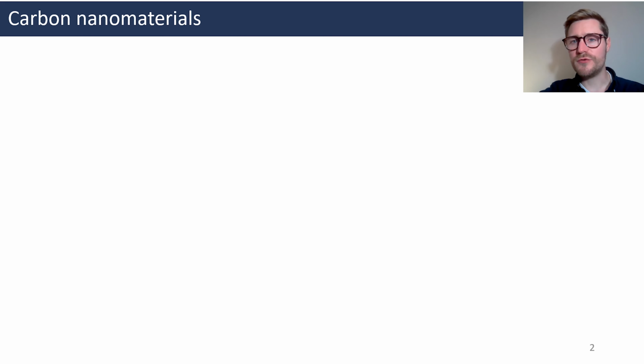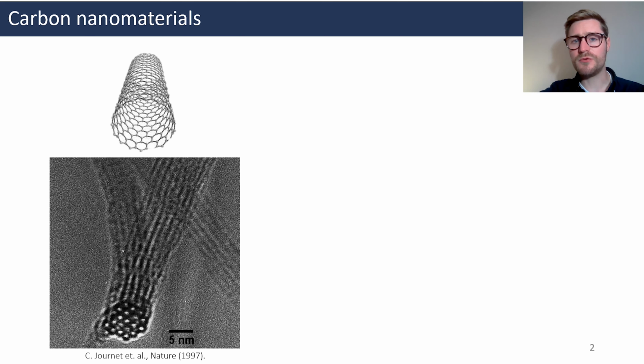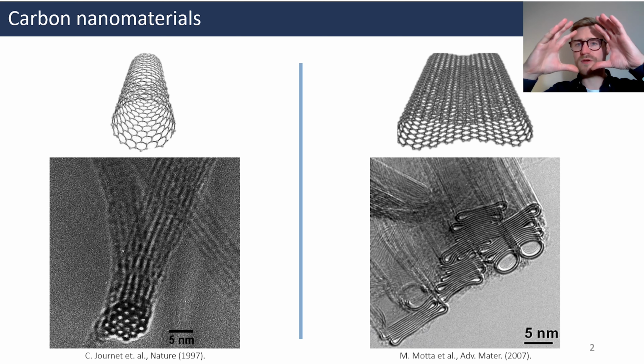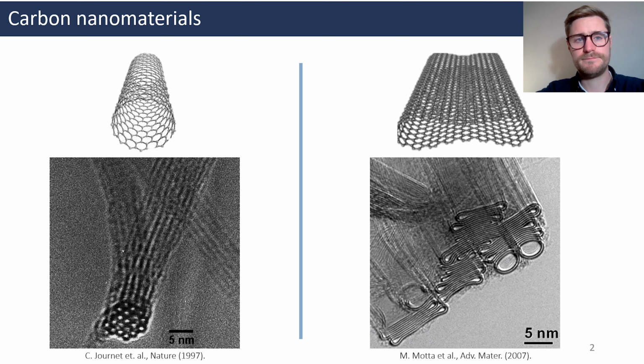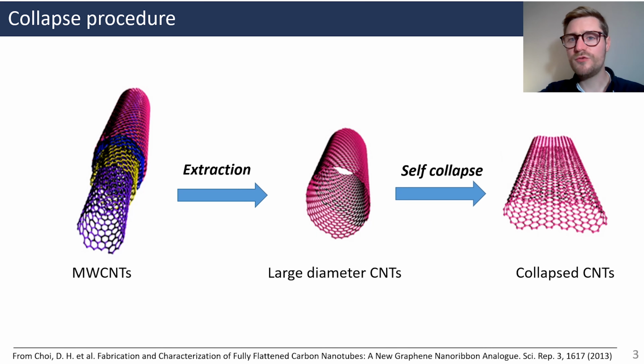If I say carbon nanotubes, you will most likely think about something like that, a cylinder. However, in certain conditions, the cylindrical shape may be unstable and tubes can prefer to adopt a flattened geometry. One way to obtain flattened carbon nanotubes is by extracting the tubes from each other from multi-walled carbon nanotubes. In doing so, you can end up with some tubes large enough to self-collapse. We did this by sonication in solution.